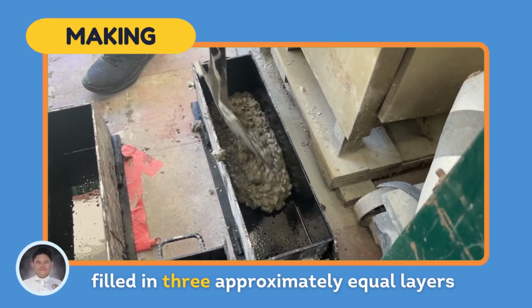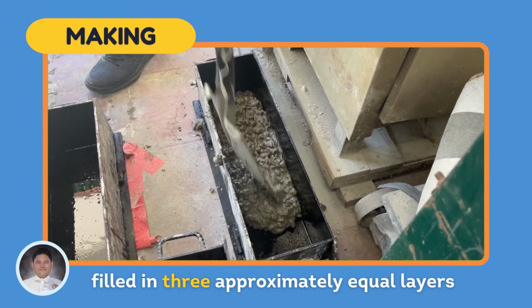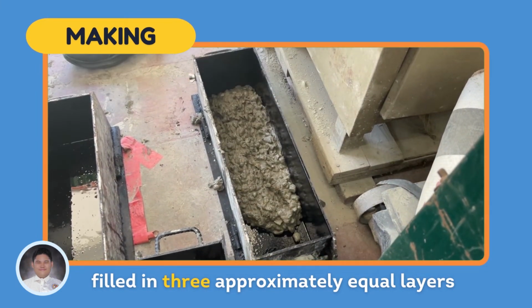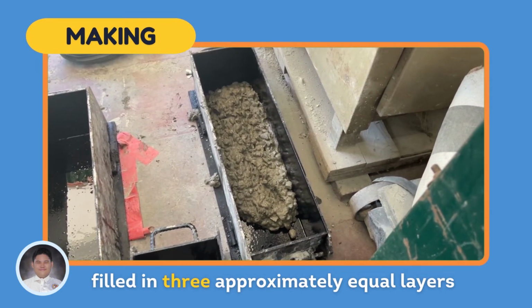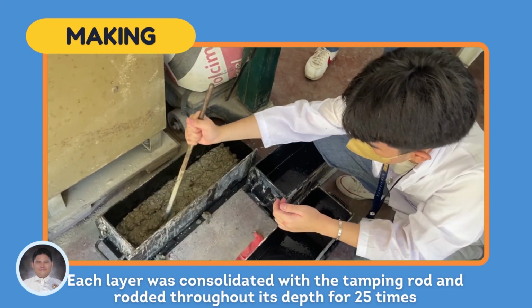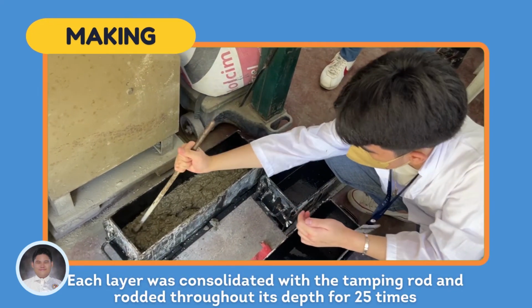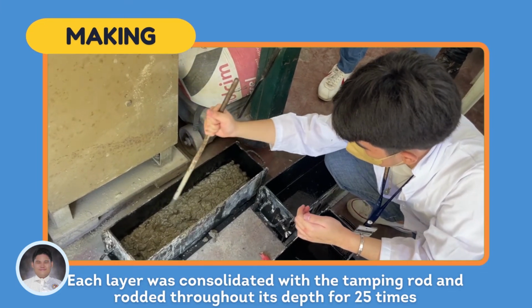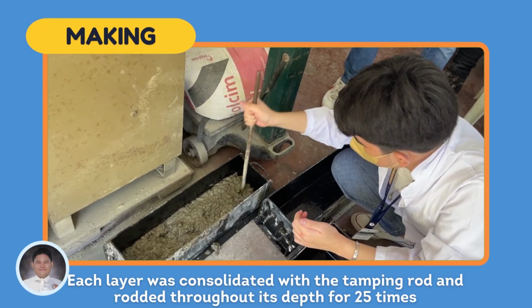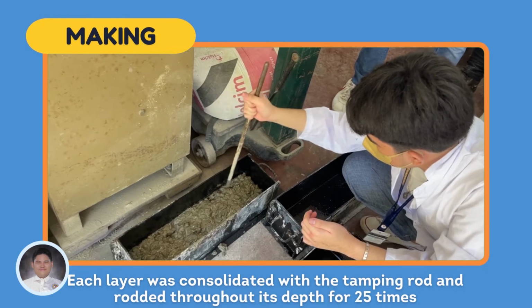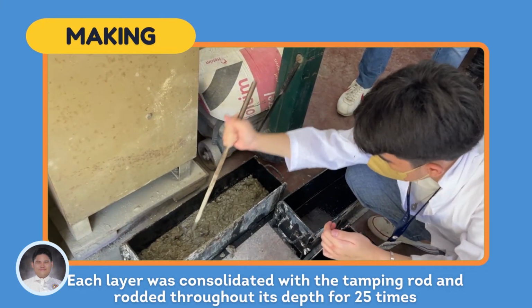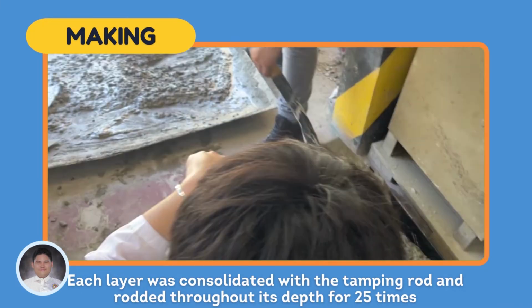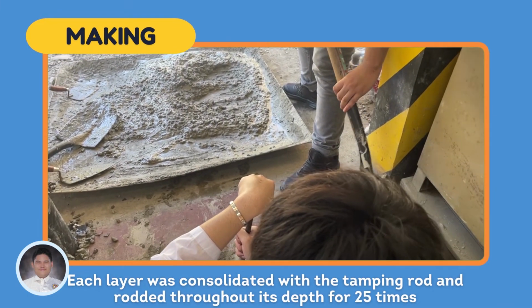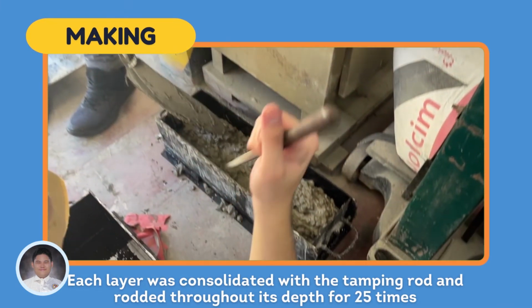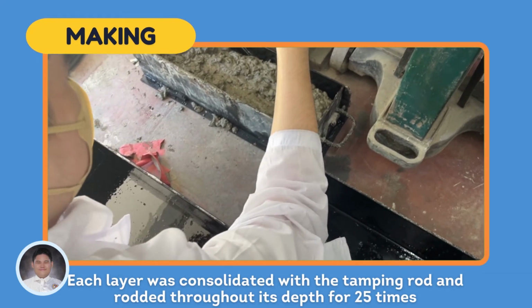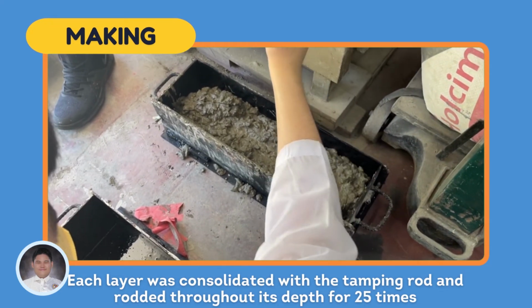The mold was filled in with 3 approximately equal layers, with the third layer slightly overfilling the mold. Each layer was consolidated with a tamping rod using the rounded end. The layers were rodded throughout its depth for 25 times, taking care to not forcibly strike the bottom of the mold when compacting the first layer. The second layer was rodded throughout its depth, penetrating approximately 25 mm or 1 inch into the lower layer.